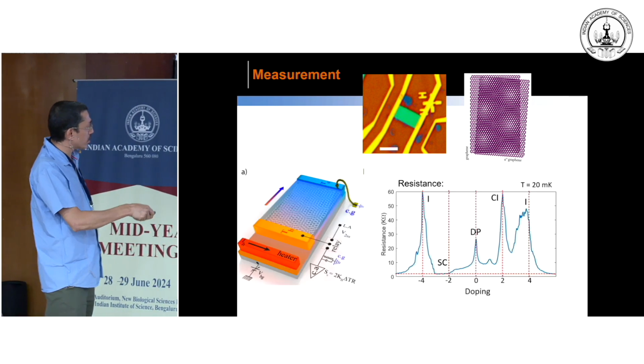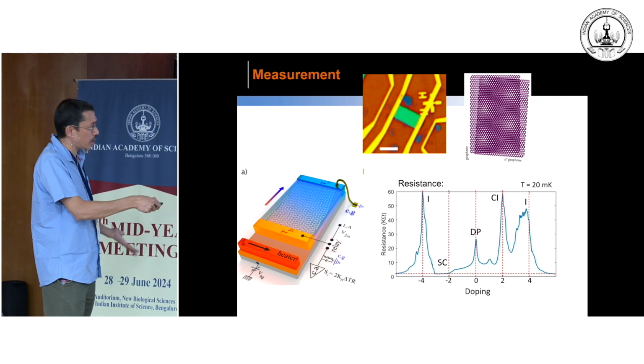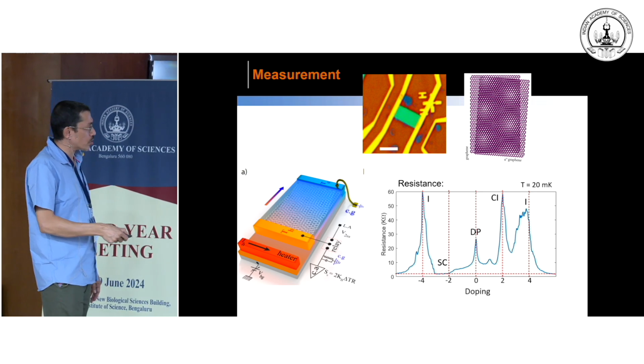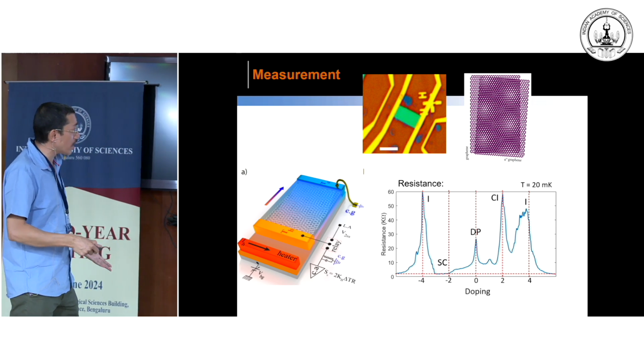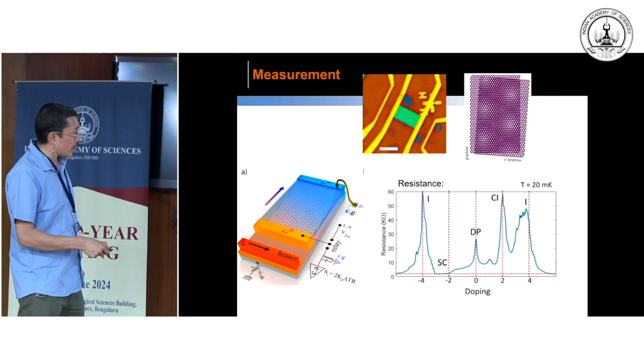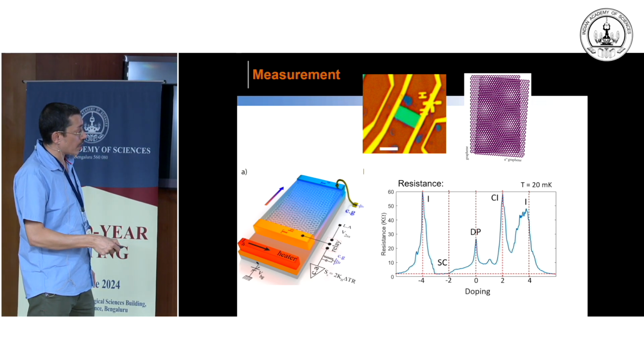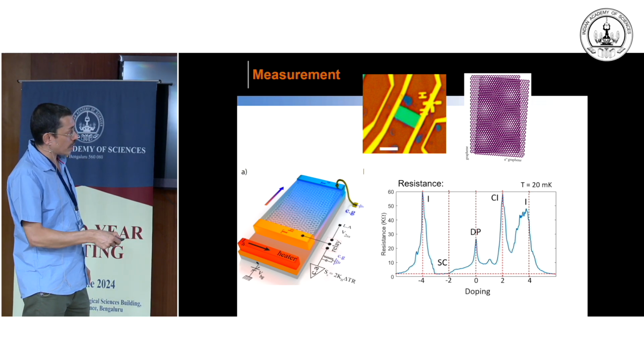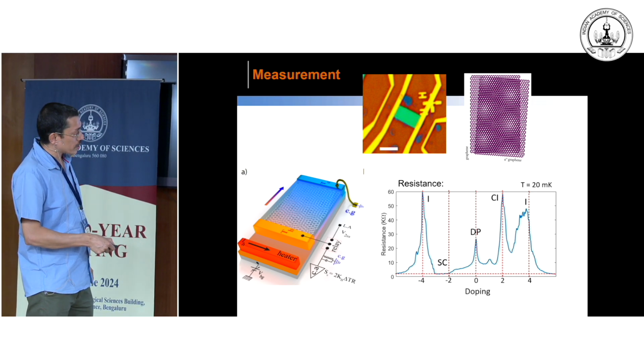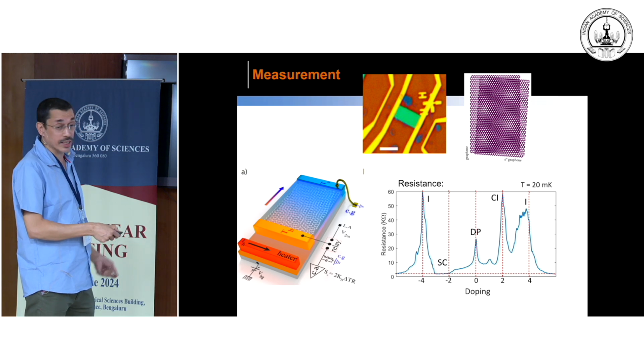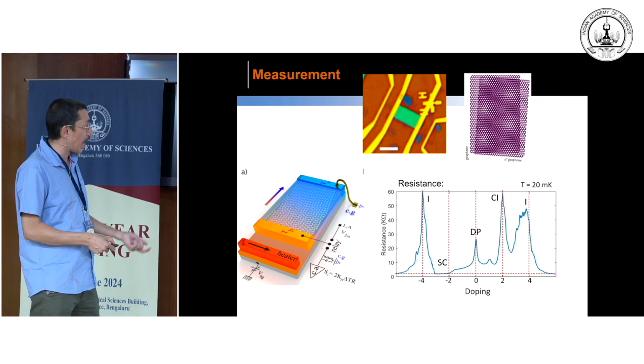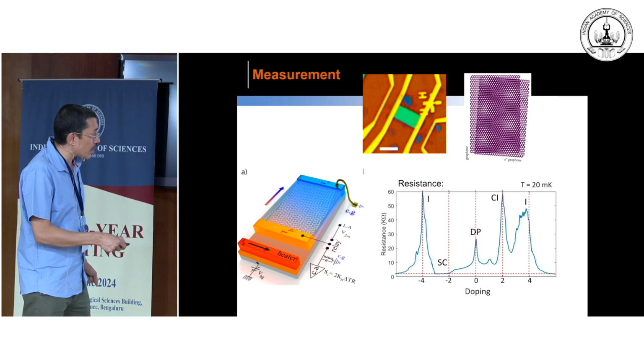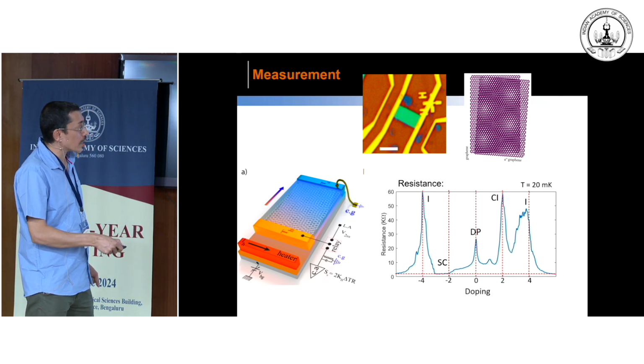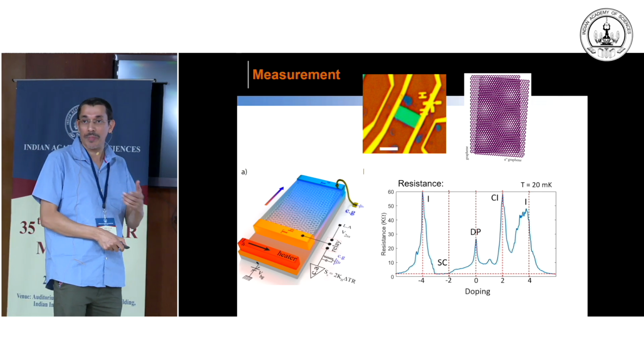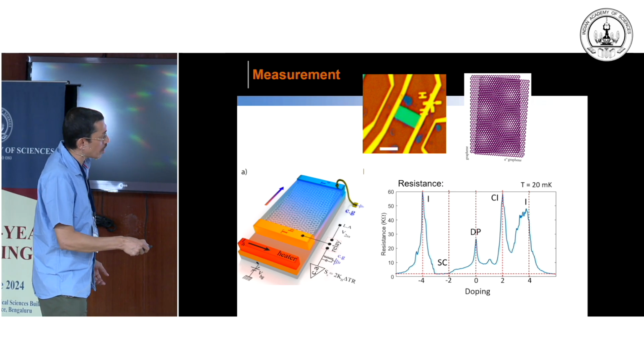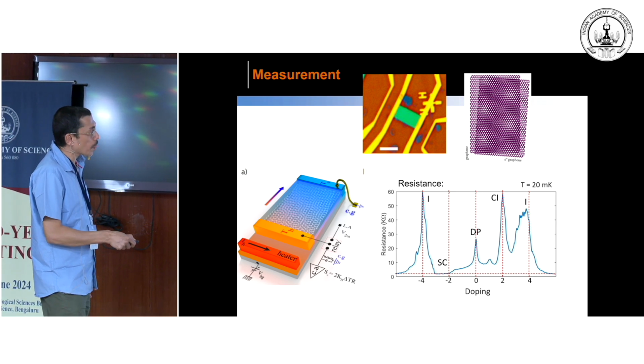The way we measure is a 2-terminal resistance measurement, a typical lock-in technique, and this is the response of our device. This is the Dirac point at 0 filling, but if you fill by 4 electrons, there is again a resistance peak. If you do -4, again you see a resistance peak. That's the band insulator I was talking about, the Moire gap. However, you see a resistance peak even at positive integer filling like +1 and +2, which you cannot describe by a single particle picture. So this is definitely coming from some correlation physics.